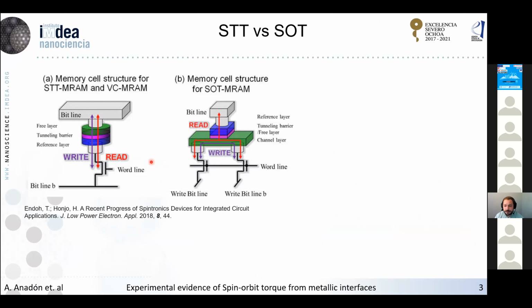Basically, there have been two main approaches for making magnetic RAM memories, and the first one, the classic approach, has been to use the spin transfer torque effect. Here we have magnetic tunnel junctions, and we already know about them. You basically have a free layer, a tunneling barrier, and a reference layer, and you have spin polarized currents going through this system, which are able to write when they are high enough. So basically, you switch the magnetization of the magnetic layer.